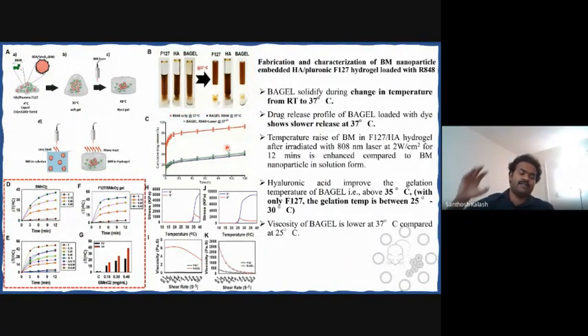A more important thing about this particular property of this hydrogel is that the BM nanoparticles, when they are in solutions, don't produce much heat upon laser, but when they are in the hydrogel formulation, they produce even more heat. You can see from this data that the MnO2 nanoparticles, at the highest concentration of 0.4 mg per ml, reached only around 37 degrees Celsius for a 12 minute time point. But the hydrogel formulation reached quickly a temperature of 45 to 47 degrees Celsius, which means that the hydrogel formulation provides this type of aggregation, which helps in producing more heat in a short period of time.